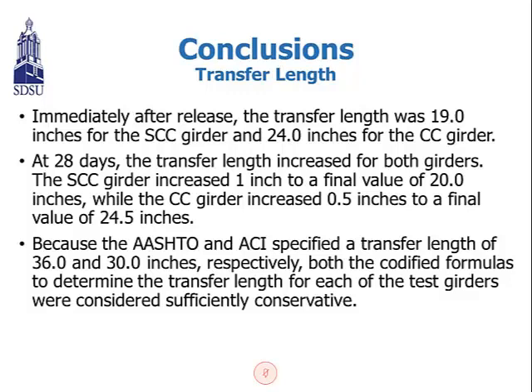And we compared the result against the AASHTO and ACI, and we got an AASHTO transfer length of 36 inches, and the ACI has a transfer length of 30 inches. Both codified formulas are considered sufficiently conservative, which is good.